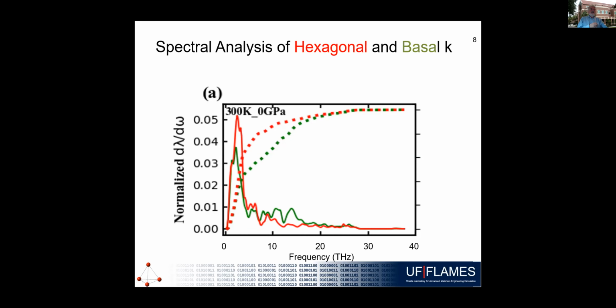And we can see here, the dashed lines are the accumulated values of that. And you can see that the accumulated values have a different dependence, depending on which direction you're going in, you have more contributions at lower frequencies than higher frequencies. So here this is saying that the frequency range which is contributing to the thermal conductivity actually depends on the crystallographic direction.